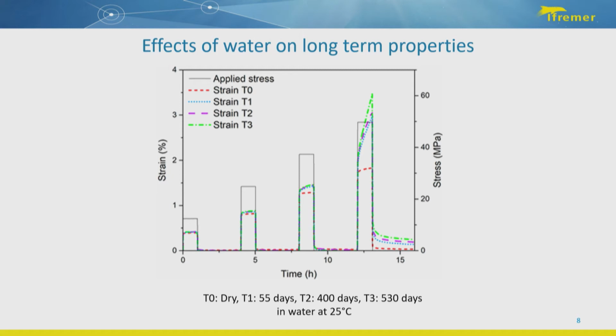So the first one is after 55 days in water at 25 degrees, and then the last one is after a year and a half. So here we can see we have at low loads a pretty elastic behavior, but gradually as we increase the loading rate, we get a bit more viscous behavior, creep. And the creep response, which in the last column is the little red dashed line when we have no water in the material, has gone to the green line when it's been in the water for a year and a half. So the viscous behavior is strongly dependent on the water in the material.